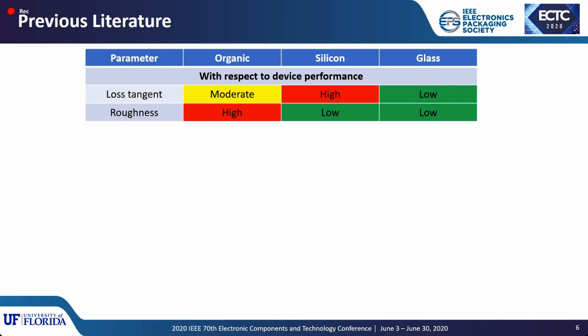If you look into the comparison chart here, we have three different types of substrates: organic, silicon, and glass. If you look into the loss tangent or the dielectric loss of the material, the organic has moderate loss at high frequencies, whereas silicon has very high loss and glass has relatively low loss compared to the other two substrates. Similarly, for the roughness values, the organic suffers from very high roughness because, in order to have good adhesion between the substrate and the copper clad, the surface of the substrate is usually roughened. And silicon and glass have roughness in the order of a few nanometers.